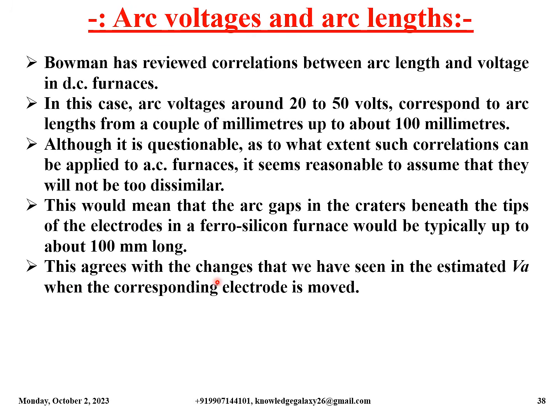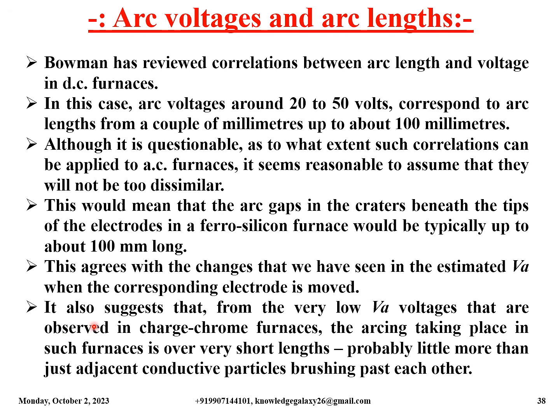This agrees with the changes that we have seen in the estimated VA when the corresponding electrode is moved. It also suggests that, from the very low VA voltages that are observed in charge chrome furnaces, the arcing taking place in such furnaces is over very short lengths, probably little more than just adjacent conductive particles brushing past each other.